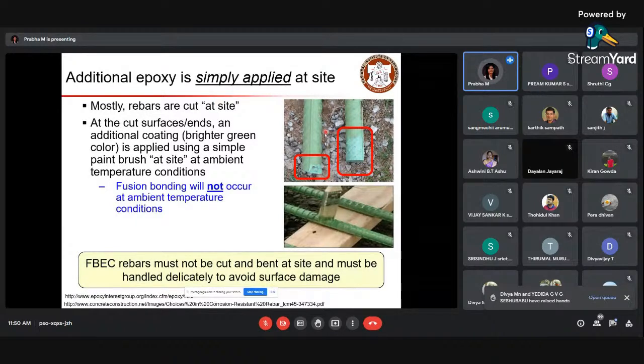Typically, when you deal with epoxy coated rebars, once it is coated, it should not be bent. But unfortunately, at these sites, they bend it for preparing stirrups. In other developed countries, how do they do it? They bend the bars first if the rebar has to be used as a stirrup, and then they coat it, so that the coating will not be damaged when it has to be used as a stirrup.